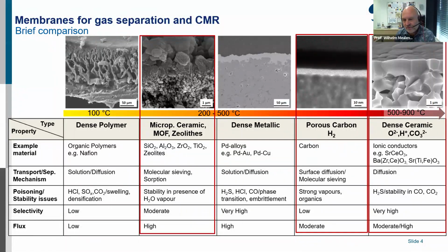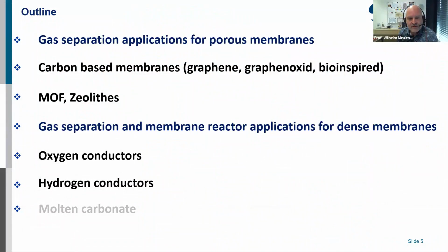In principle, we can differentiate polymer membranes, which are applicable in the low temperature area up to 200 degrees C. Then we have the metal membranes, for example, the palladium membrane, somewhere in the range of 300 to 500 degrees C. And I want to focus in my talk today on the ceramic membranes, and there we have the microporous membranes, the metal organic frameworks and the zeolites, and we have the ionic conductors, which maybe for most of you are of interest in this talk. Therefore, I made an outline. In principle, I want to focus on porous membranes.